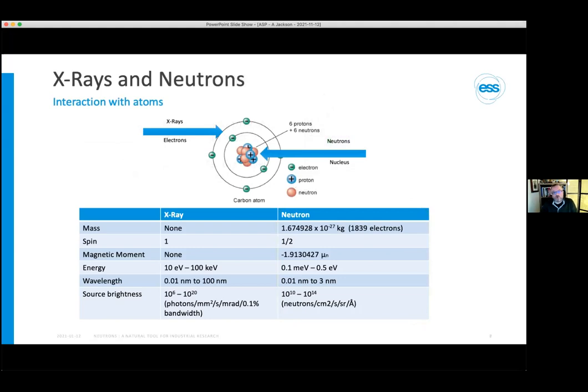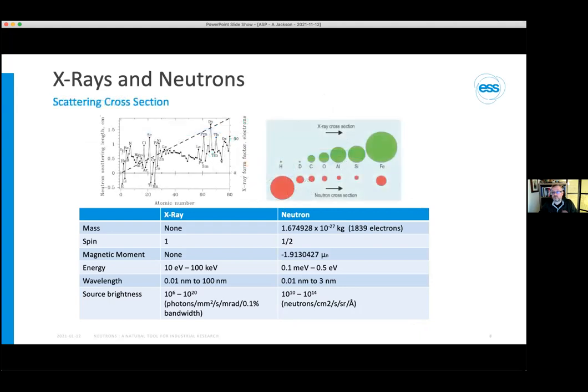Another difference is that x-rays interact with the electron cloud of an atom, whereas neutrons — being charge neutral — interact with the nucleus and scatter from the nuclear potential. These two probes therefore have different sensitivities. On the left we have the neutron scattering length as a function of atomic number, which varies somewhat randomly across the periodic table. The x-ray form factor for electrons, by contrast, is more or less linear with atomic number — just going with the number of electrons in the atom.